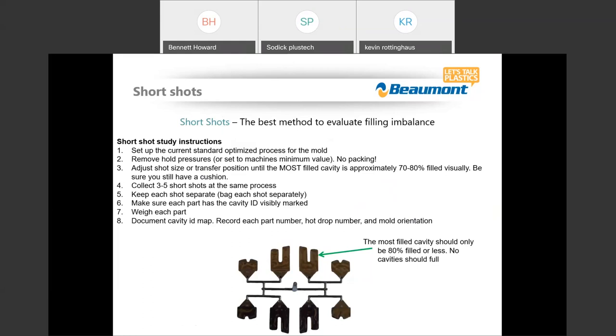At that point in time, for the most part, most tools look very uniform because we've created a lot of hesitation. We've got some cavities at around 98% full, 95% full. Other cavities are starting to catch up already. We hesitated the flow front. Other cavities are coming up to those cavities, and we end up maybe making ourselves feel better about the balance of the tool because the numbers look closer, because we introduced hesitation. The plastic became harder to fill to those first-to-fill cavities, so it simply went to where it's easier to flow. Plastic always goes to where it's easier to flow. So when a flow front hesitates, it just goes somewhere else if that option is available.